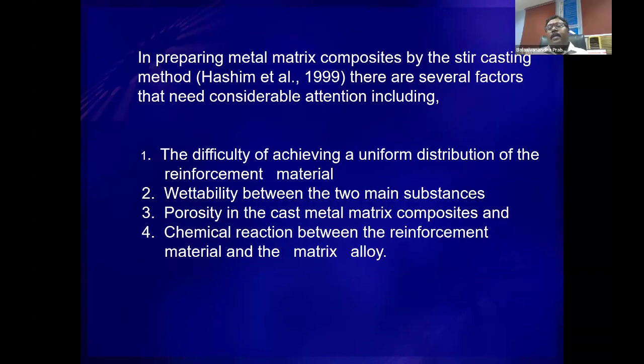In general, even though this technology gives the possibility of mass production, there are some challenges associated with it. One is the difficulty of achieving a uniform distribution of the reinforcement material. That is the foremost challenge of this technology. Once you achieve a homogeneous distribution, you can also work on improving the properties of this material. Another is the wettability issue, because you try to bind a metallic material and a ceramic material, and as a result wetting would be a problem.